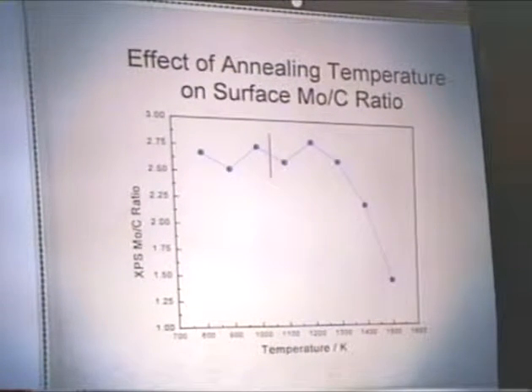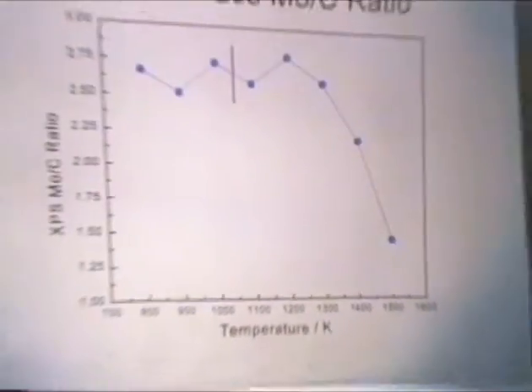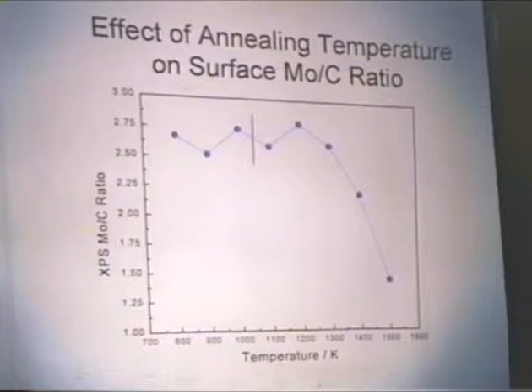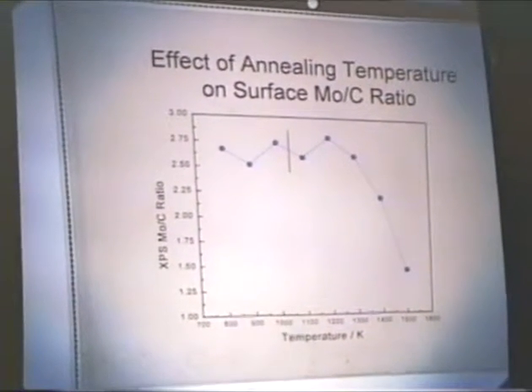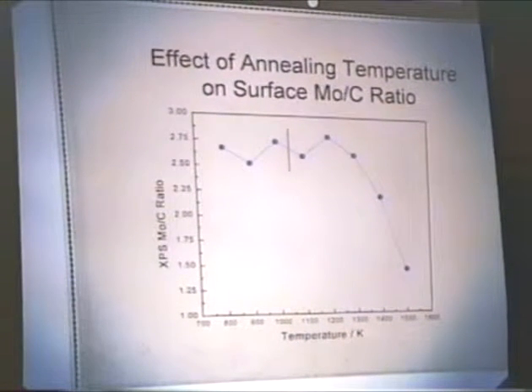As indicated by the red line, at 1050 Kelvin or higher for annealing temperatures, we detect iron contamination on the surface. We have since found out that this is coming from sublimation of our stainless steel set screws. And so this limits us in our surface preparation to temperatures below 1050 Kelvin for annealing. The drop-off seen above 1300 Kelvin, we are going to have to explore once we have modified our sample mounting procedure, because we are not sure whether this is a true phenomenon or whether it's related to the fact that we get a large amount of iron deposited once we get to those high temperatures.